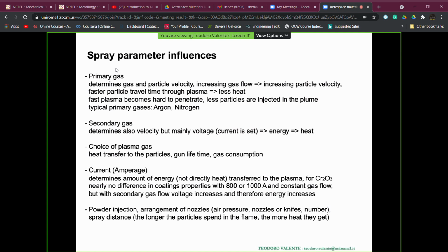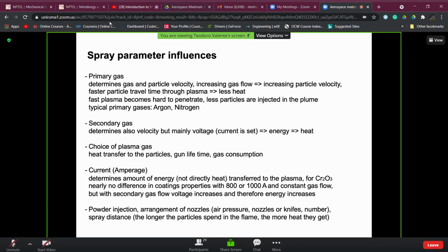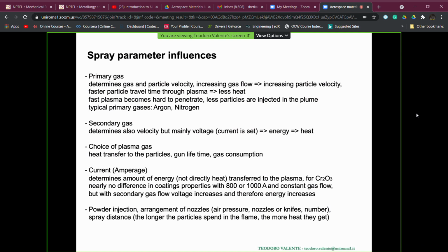flow. But just to tell you that if this is the case, we use the lowest value, that is, we are consuming less energy. But with secondary gas flow, voltage increases, and therefore also the energy increases in this case. The powder injection is another important parameter. So the arrangement of the nozzles, which are used to inject powders into the plume, that is, for example, the number, that is the pressure, it's important, of the flow transporting the particles itself.